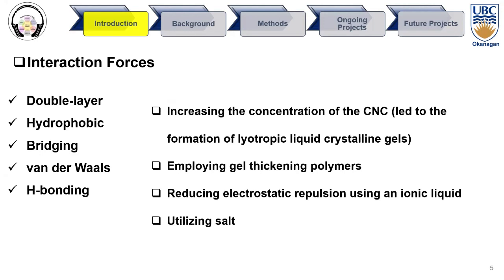Also, we can use some polymers like gel thickening polymers, and we can reduce electrostatic repulsion by ionic liquid. But the most important and easiest and most straightforward one is using salt. By using salt, we can reduce the Debye length, and also we can increase the viscosity of cellulose inks.